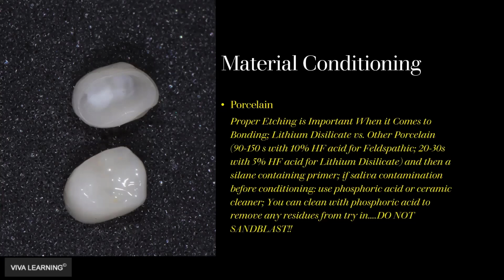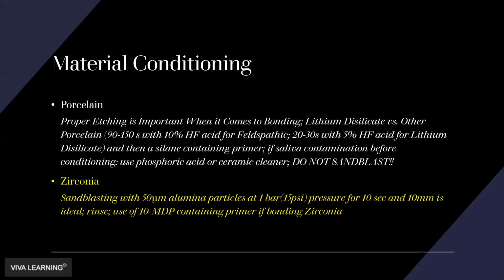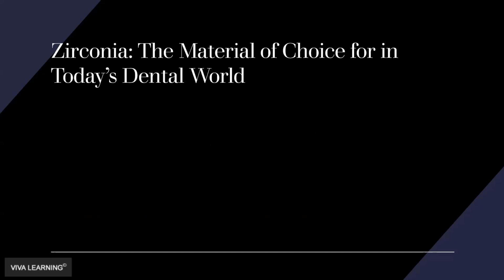And of course, the next material that we're talking about is the one that's most popular, zirconia. Zirconia is the material of choice nowadays in today's dental world. In other words, it seems to be the most rapidly rising material in use. And of course, the key with it is that you have to sandblast the inside of it with a low pressure for 10 seconds. And we want to hold that at a distance of 10 millimeters. And of course, if we're going to be bonding it, we have to have a primer that has the 10 MDP containing primer in it. That's the secret sauce that helps us bond to zirconia.